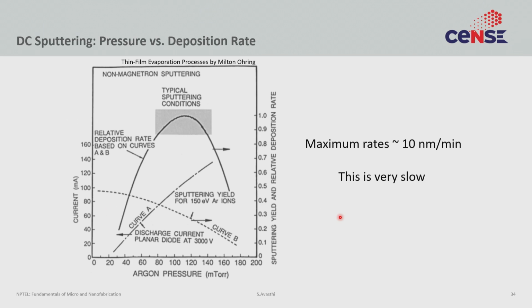This is the same thing as being demonstrated on this very nice graph from a book by Milton Ohring. This book is, by the way, freely available on the web as an e-book by the publisher. I urge you to read it, it's a remarkable read. So this is the same thing that we just discussed is shown here. So you have sputtering yield and relative deposition rate on the right hand side. You are looking at the current, which is nothing but ion flux inside the sputtering chamber, on the left hand side. And you see that under typical sputtering conditions, you actually get this U-shaped curve, right?